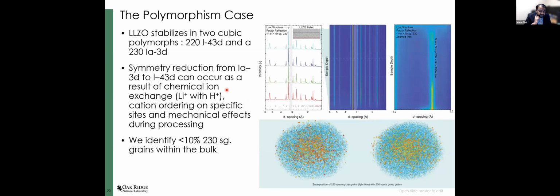And so we went back and looked at the diffraction microscopy data, and we found that while we could fit a bulk of the grains to the 220 space group of this garnet material, there was a smaller fraction of grains that we could also fit using a 230 space group. Now, these LLZO materials, the lithium lanthanum zirconium oxides, are strange in the sense that they stabilize in 2 cubic polymorphs. One is a lower symmetry 220 space group, and one is a higher symmetry 230 space group.